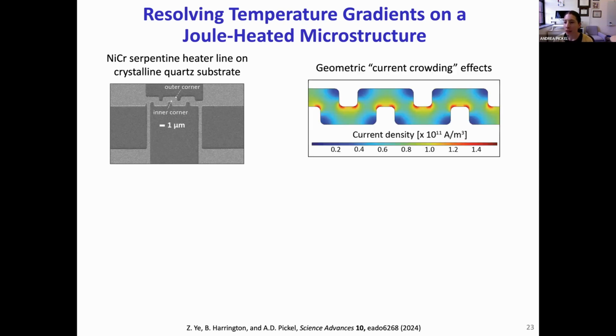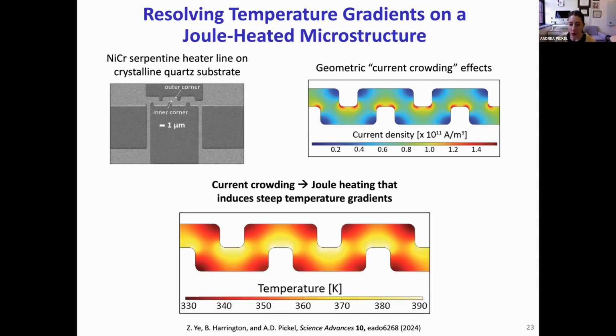So finally, we wanted to show that we could really use this technique to resolve temperature heterogeneities that can't be seen with diffraction-limited measurements. To do that, we need test structures that can generate steep temperature gradients. So we fabricated microscale serpentine heater lines made of nichrome on quartz substrates. When you send an electrical current through these heater lines, the current density concentrates at the inner corners due to a geometric effect that's called current crowding. And so the resulting joule heating also concentrates at the inner corners, and you get temperature gradients where the inner corners of the heater line are at higher temperatures than the outer corner.